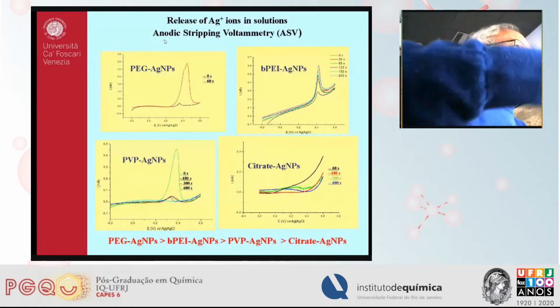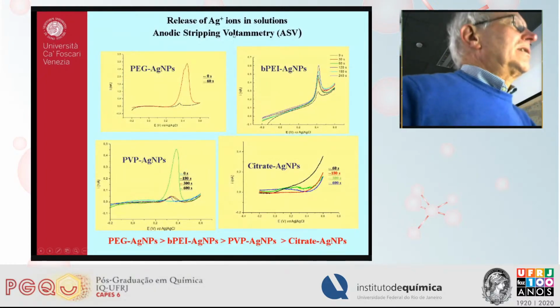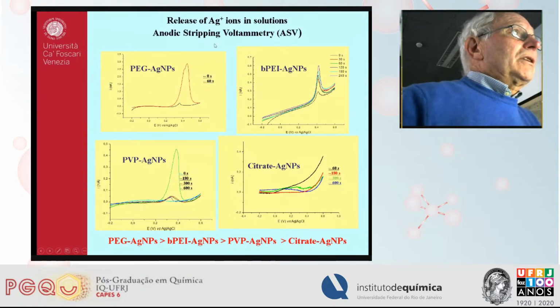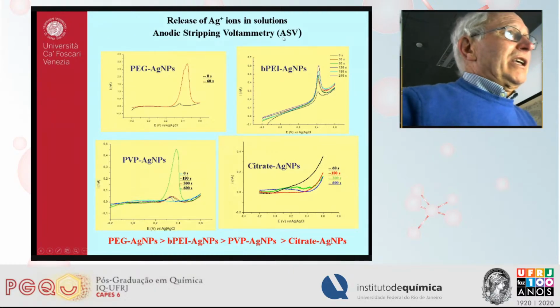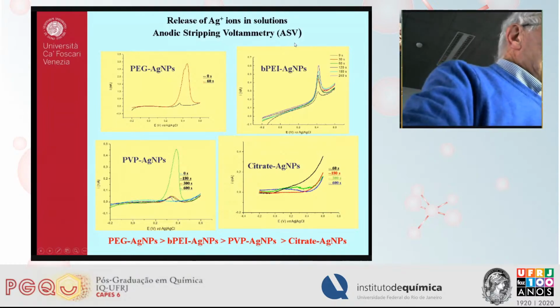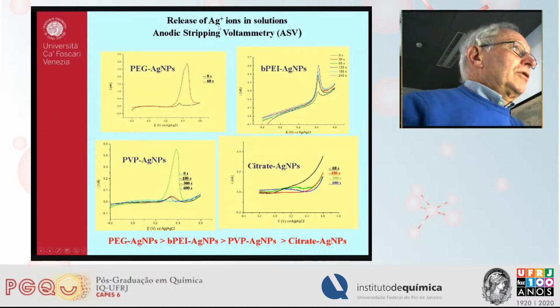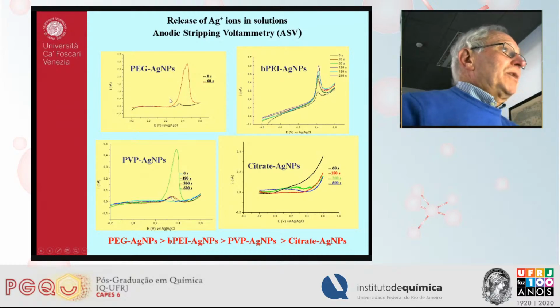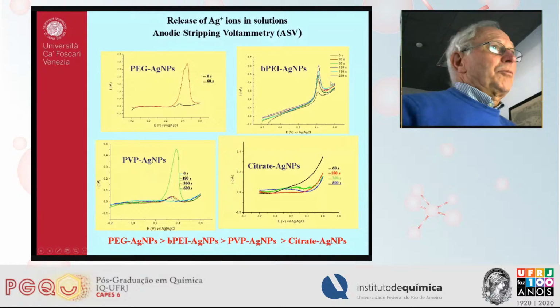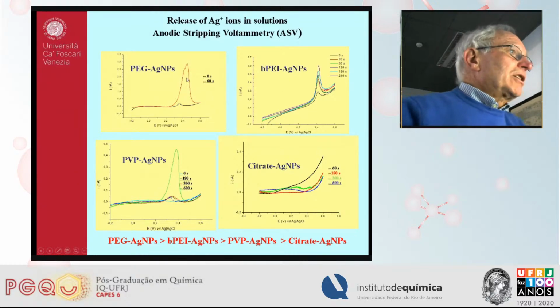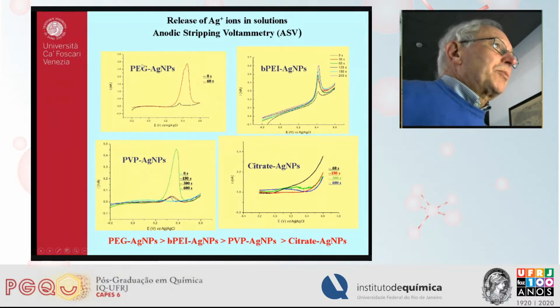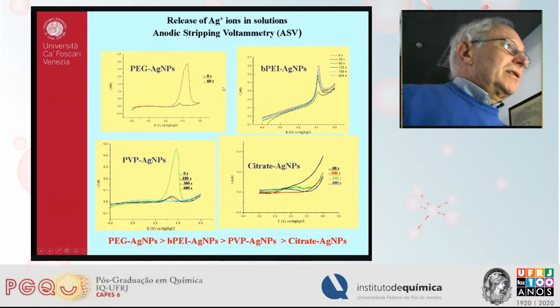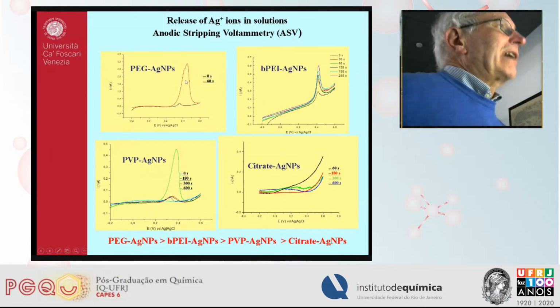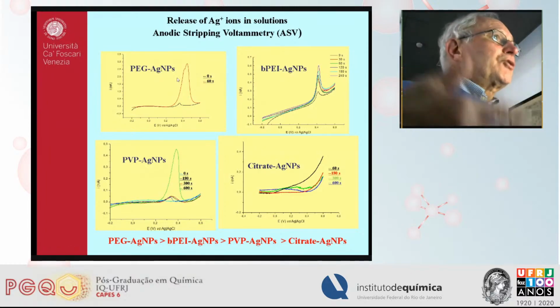So in order to detect the amount of silver ion released, we can use this technique, which is called anodic stripping voltammetry. It's similar to the technique I mentioned before, adsorptive stripping voltammetry. In this case, we reduce silver ions on the surface of an electrode and accumulate metallic silver on the surface, which can afterward be oxidized to get this kind of peak. The peak area or the peak height of these responses can be used to detect the amount of silver ion released. Exploring these four different types of silver nanoparticles, we verified that the stability and reactivity in terms of releasing silver ion are much different.